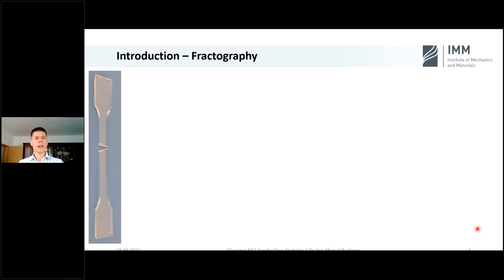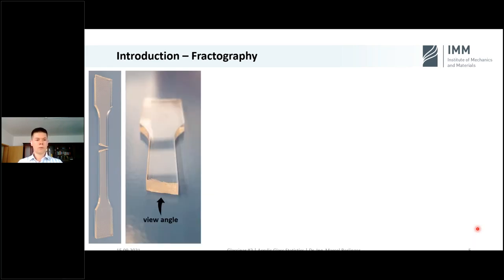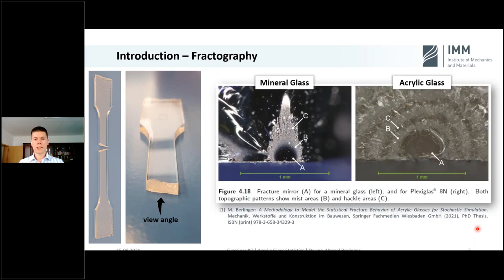Here is one of the specimens I tested. When we view the specimen on fracture surface, we have, analogous to mineral glass, so-called fracture mirrors. Here, a picture out of my PhD thesis. And these fracture mirrors are a good hint where the fracture did develop, where the crack did develop, because they are developed right in the center. And that could be good in the detection of outliers later on in the sample.